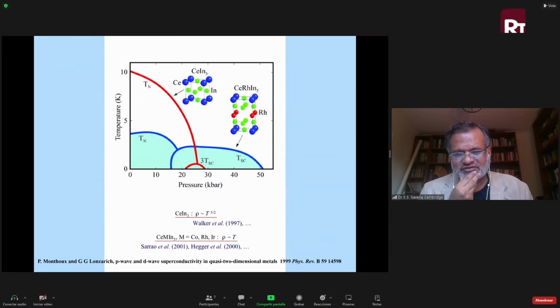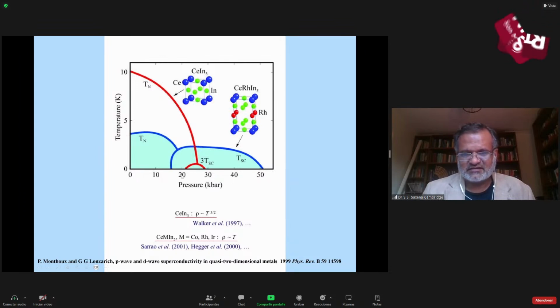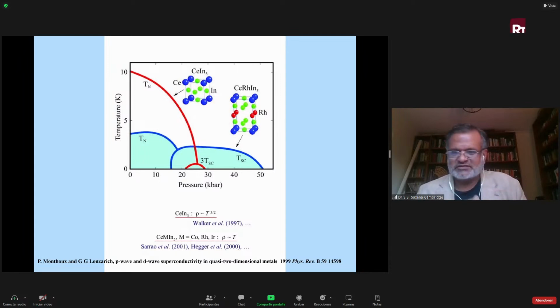So there are two things to focus on as we progress with this talk. The first is what I just described: how superconductivity happens when this state is suppressed, and the nature of the fluctuations which emerge, meaning the ordered state starts to become unstable. It's fluctuating, but fluctuating in a metallic system. So as the electrons cool down and lose their primary thermal characteristics, they get scattered by these new fluctuations. That's part A of the new physics. Part B is that when these electrons scatter from these fluctuations, they actually damp the fluctuations, and that is how we understand the emergence of the non-Fermi liquids, the novel metallic state, and the superconducting state that follows it.